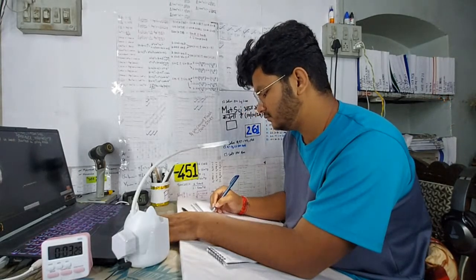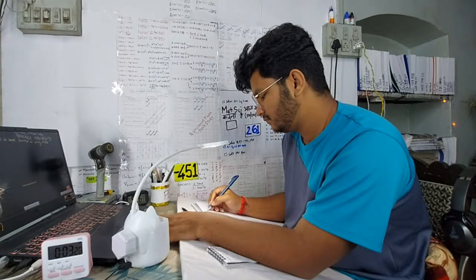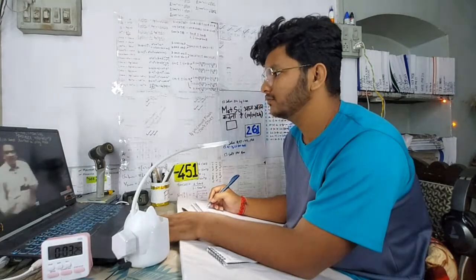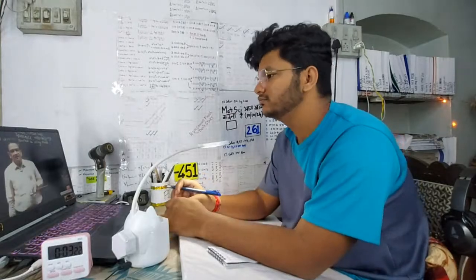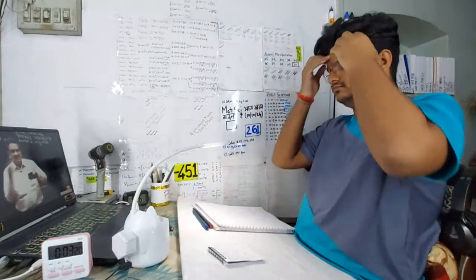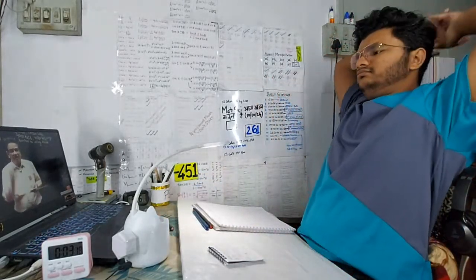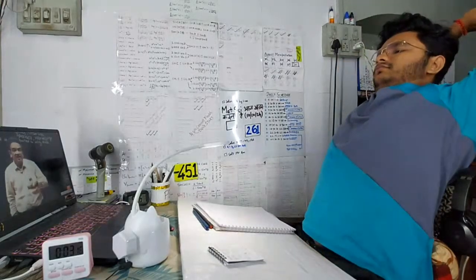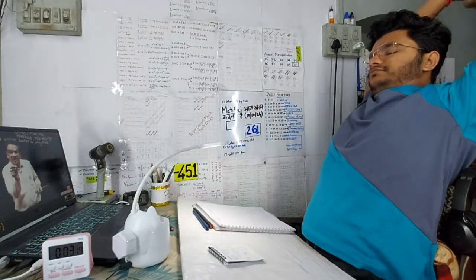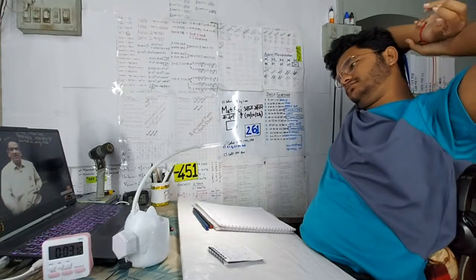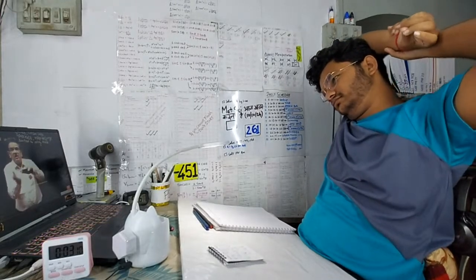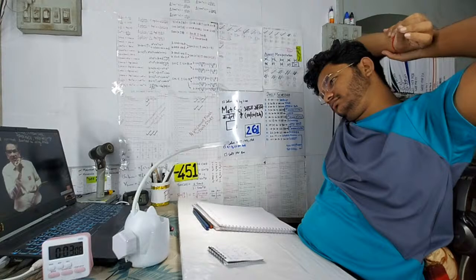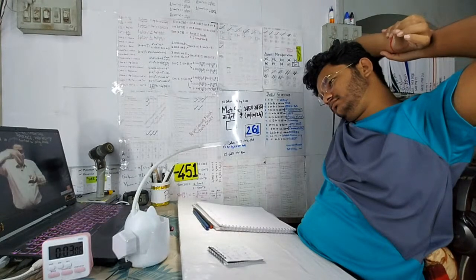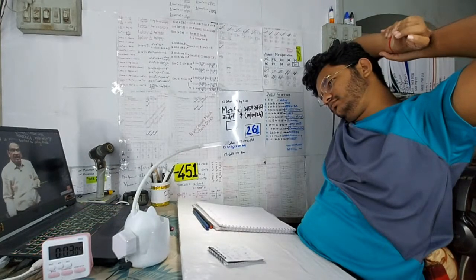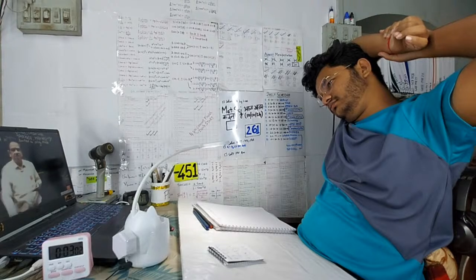Next, what are we going to do in the case of the nitriding process? We take an alloy steel specimen. We heat the alloy steel specimen in the presence of either dissociated ammonia or molten sodium cyanide salt. What happens on heating? The nitrogen atoms will diffuse into the surface of steel. That results in formation of iron nitrides.